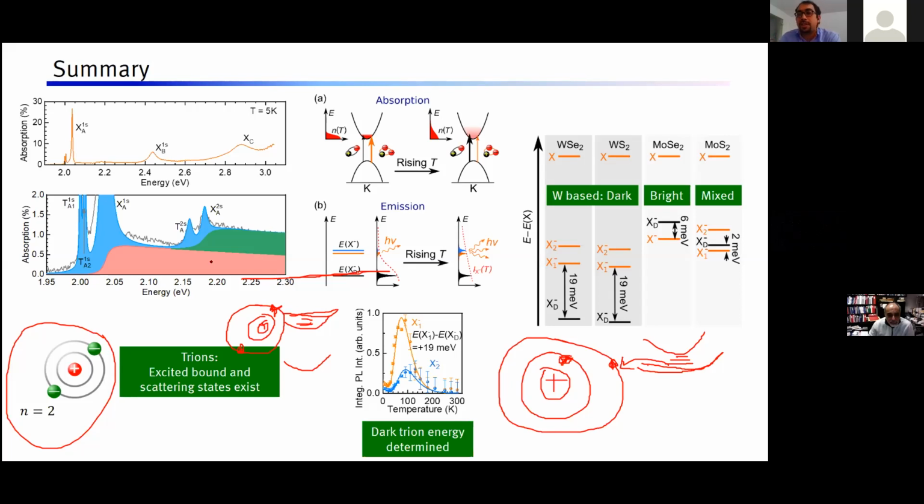Definitely. The oscillator strength strongly depends on the effective masses, number one, which dictates how strongly the exciton or trion would be bound. So the exciton binding energy depends on this strength, and this will also decide the oscillator strength of these resonances, these species. Can we say that systems with lighter effective masses do not have many of these? This statement would be in general correct.